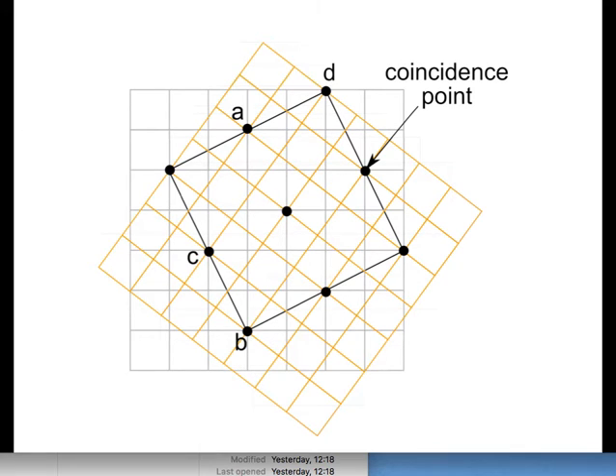Now going back to our coincidence site lattice, I said to you that this is a lattice vector of the CSL, and it's also a lattice vector of your orange lattice and a lattice vector of your gray lattice. That means its components are integers. This is a primitive lattice that I've drawn. Its components are integers. It'll be like 2, 1 in the case of the gray lattice, and 1, 2 in the case of the orange lattice, and just 1, 0, 0 in the case of the coincidence site lattice.